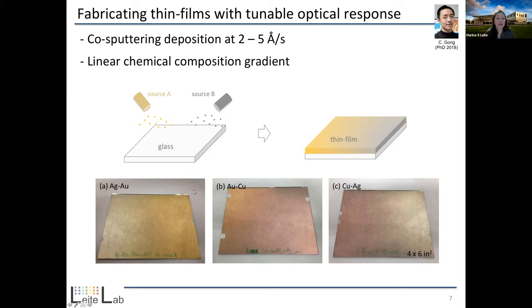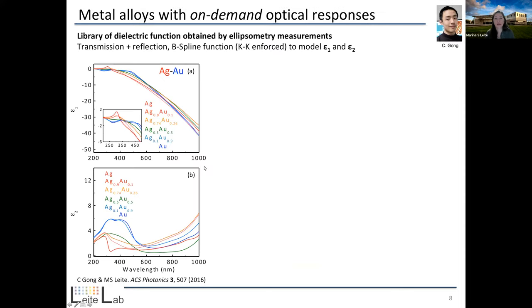Okay, and then once we characterize the chemical composition very well, when we know we have a very smooth gradient in chemical composition, we can then go ahead and measure what we call ellipsometry. So when we measure ellipsometry, we're essentially combining transmission and reflection measurements, and then we have to model using a mathematical function what is the ultimate permittivity, again, epsilon 1 and epsilon 2 here, of the material that we have.